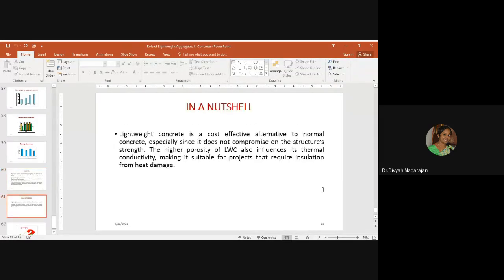satisfied. Therefore, in a nutshell, the lightweight concrete, not only the sintered fly ash aggregate concrete, but in general, lightweight concrete is a cost-effective alternative to normal concrete, especially since it does not compromise on the structure's strength. The higher porosity of the lightweight concrete also influences its thermal conductivity, making it suitable for projects that require insulation from heat damage.